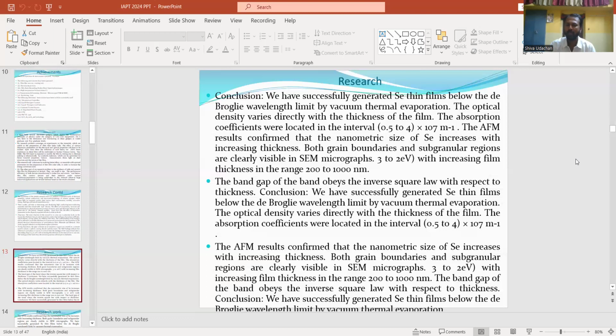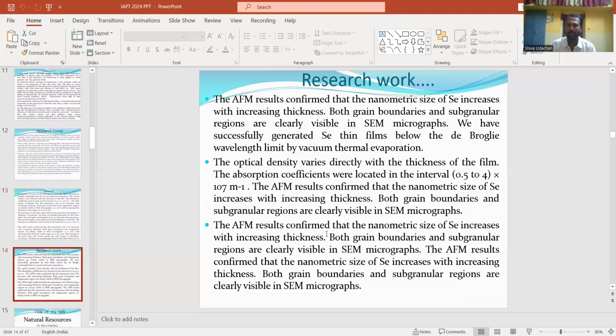Conclusion: we have successfully generated selenium thin films below the de Broglie wavelength limit by vacuum thermal evaporation. Now, moving to the next slide. That is, the AFM results confirm that the nanometric size of selenium increases with increasing film thickness. Both grain boundaries and subgranular regions are clearly visible in SEM micrographs.